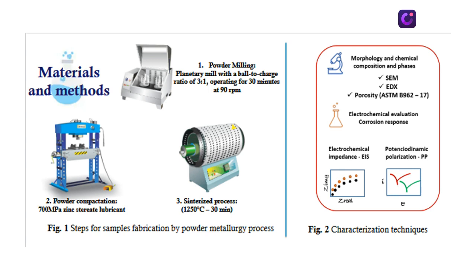The procedure starts with the homogeneous mixing of the steel powder with silicon carbide particles in a planetary ball mill with a ball to load ratio of 3 to 1, operated for 30 minutes at 90 RPM, varying the reinforcement content as indicated above.